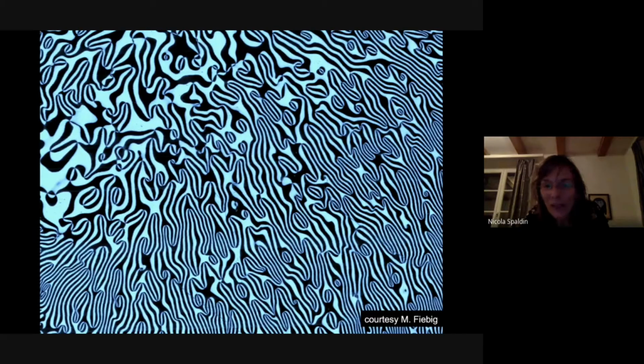Also because those of you who looked at ferroelectric domain structures will probably never have seen anything like this unless you've looked at multiferroic yttrium manganite. It's really unusual. It's absolutely not at all what one expects to see for a ferroelectric domain structure. Usually they're kind of stripes or square-shaped things, but this is extremely exotic. The unusual features are related to the fact that it's multiferroic, or the unusual nature of the ferroelectricity permits it also to be magnetic and to be ferroelectric at the same time.